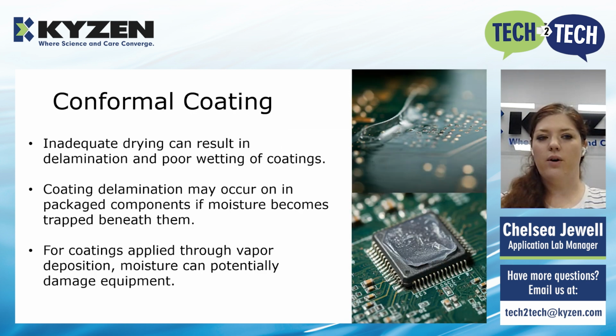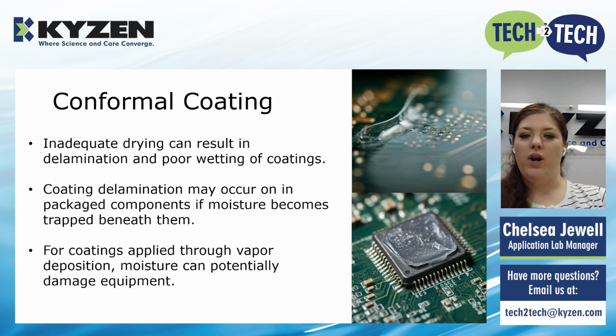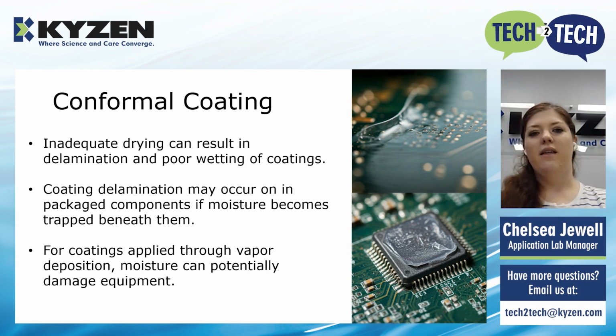So looking into conformal coating, if we are seeing a couple different areas of failure with conformal coating, we can lean back into what's going on in that dryer section to help figure out what's going on there. So delamination, what you're seeing in both of these images, is that coating is actually peeling up off of the surface of the board. This can be due to high moisture. There's a couple other areas it can happen, but drying is usually something that we start that process to troubleshoot. Poor wetting of components, you can see haziness in the conformal coating. All of these can lead to an indication that the board's not completely dry before the coating was applied.